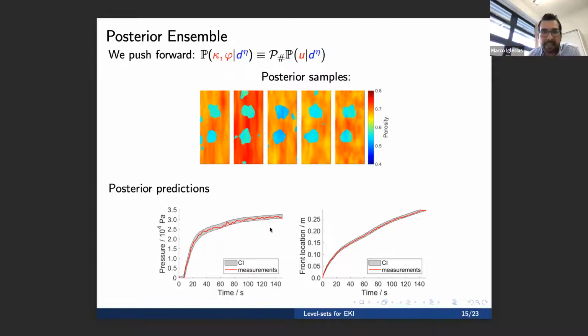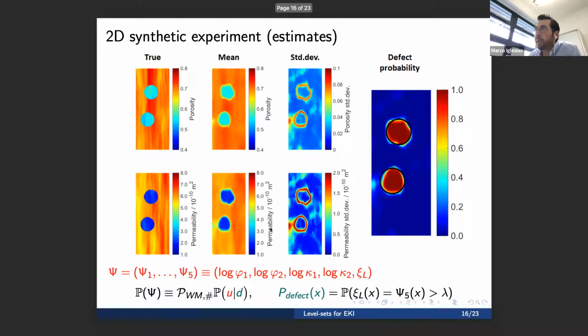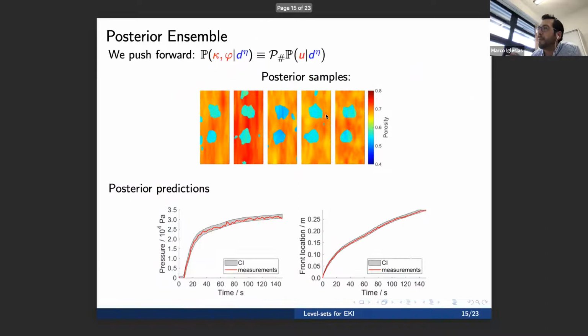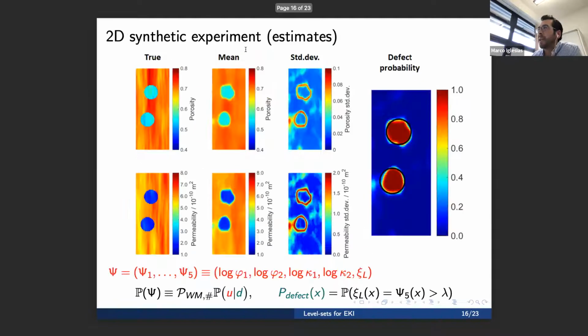Well, obviously, it's a synthetic experiment. Everything works well with a synthetic experiment. Right? But let's do real data now. Oh, well, before I go into that, I haven't shown you actually the main results. So from this posterior ensemble, we can compute the mean of these particles, which is what I show here for the porosity and for permeability.